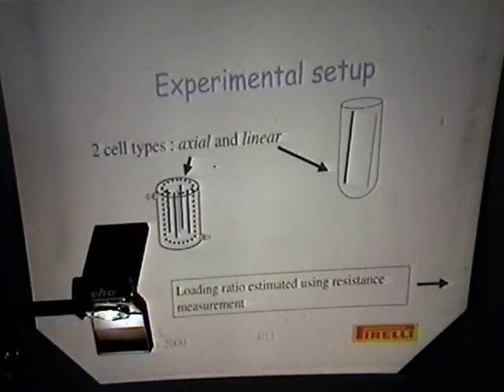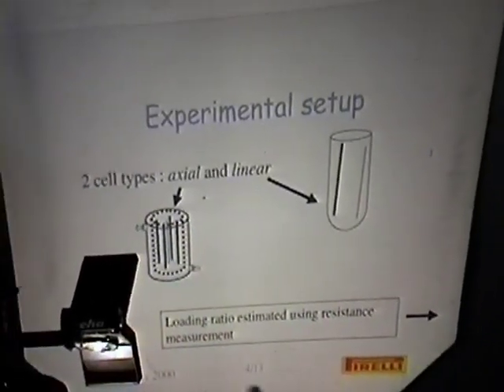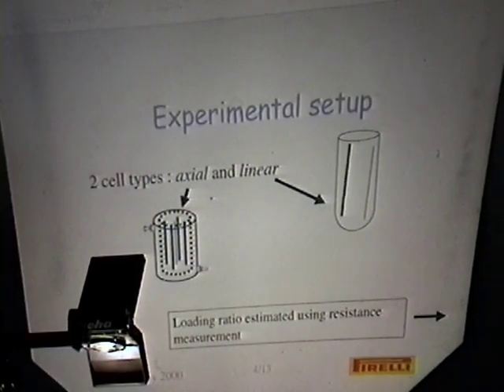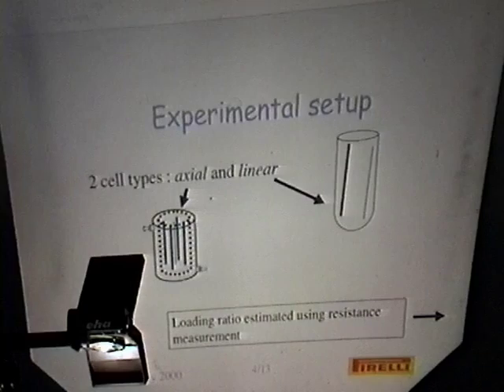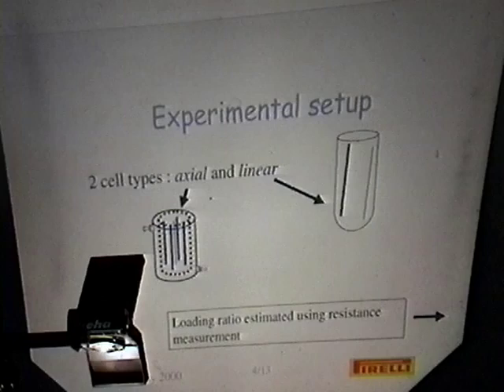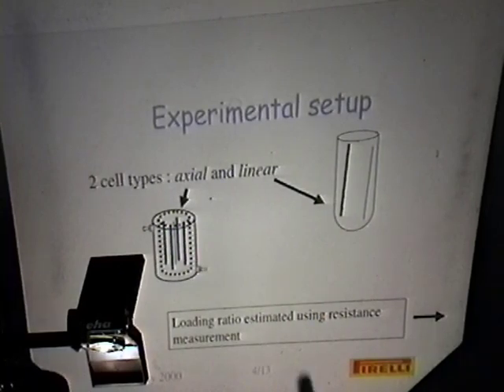I'm going to describe schematically our experimental setup. These are the schema of our two cells. I call the first axial, the second linear. We use a palladium wire 50 microns in diameter and about 10 centimeters long in both cells. In the first one, there are two wires, the palladium wire and the platinum wire, 500 microns in diameter and of the same length as the palladium wire, and they are parallel, almost vertical. The second one is similar, but we have the anode composed of 4 platinum wires disposed in a symmetrical way. They are electrically connected in order to form a unique anode.